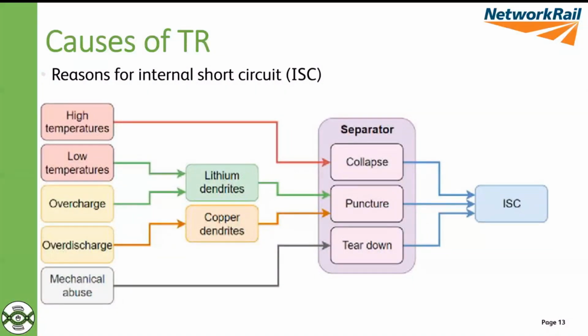So this is a real problem, and it's exacerbated by very fast charging at low temperatures, which can actually result in poor performance of the battery. And this is one of the reasons why you get a short circuit in the battery system and you get a fire.